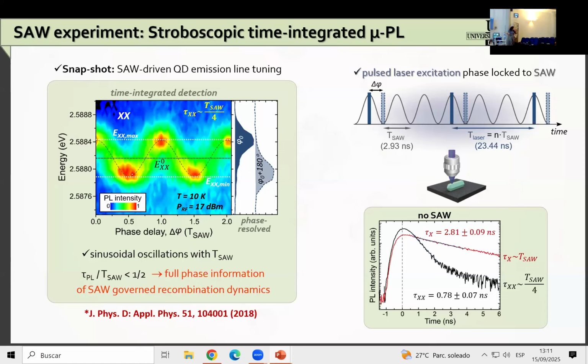So then, depending on the lifetime, we can basically see such oscillations when we perform the time integrated detection. So the difference was that in this case, we have time integrated detection, and the other case was time resolved, right? This we cannot see in the case of the exciton because it has a long lifetime. So basically, this modulation is kind of smeared out. We can only observe it for those transitions which have a lifetime that is shorter than the acoustic period. So that's the difference. In one case, we have time resolved detection. In another case, we have time integrated detection. But in both cases, the excitation is pulsed, and it's synchronized with the acoustic wave.